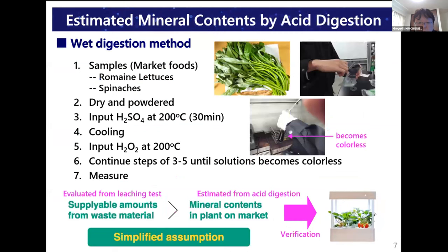Thus, we got supermarket food of romaine lettuce and Chinese spinach. We measured their chemical compositions according to acid digestion. Samples were dried and powdered with milling. And then the powdered ones were completely dissolved with two types of acid. Finally, the liquid obtained from this process was analyzed using ICP and ion chromatography. Therefore, a supplyable amount can be evaluated from the previous leaching test.